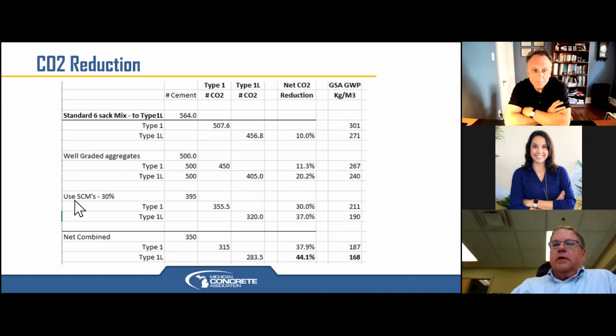The other thing we've been using very religiously is supplemental cements, fly ashes and slag cements. With a 30% replacement of slag cement, there's a 30% reduction in global warming potential, right? If we use the type 1L in conjunction with that, it's a 37%. So net combined today, we are making concrete in Michigan that's 44% lower in global warming potential than we did 20 years ago. We are already doing what Arnold said that he thought the Europeans were doing.